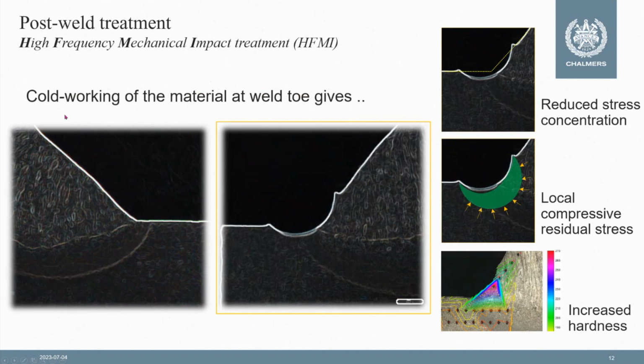This cold working that takes place very locally at the weld toe region has three principal influences that are important for the fatigue performance. The first one is that it deforms the material at this location and reduces the stress concentration, giving a smoother transition from the weld metal to the base metal in this region.